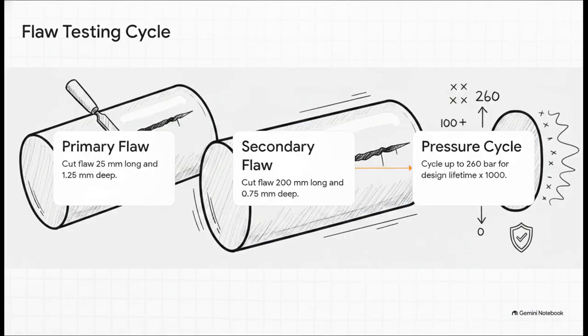The sheer brutality of the flaw testing is just fascinating. To prove these cylinders won't catastrophically blow up from a random scratch they picked up under a truck, testers must literally carve deep, specific longitudinal flaws right into the sidewall. Once it's intentionally compromised like that, they aggressively cycle the pressure from 0 all the way back up to 260 bar.